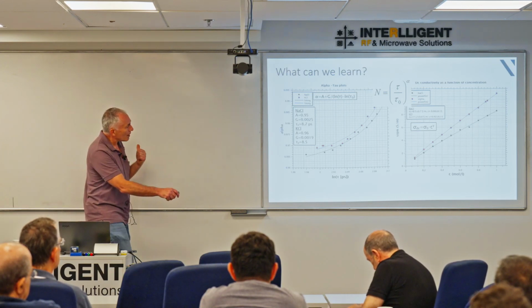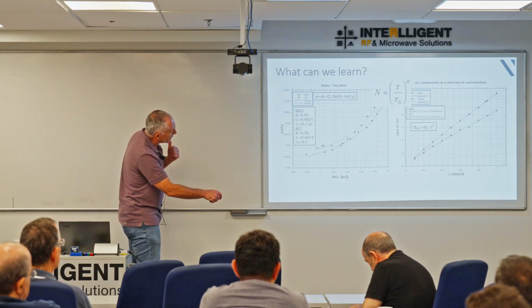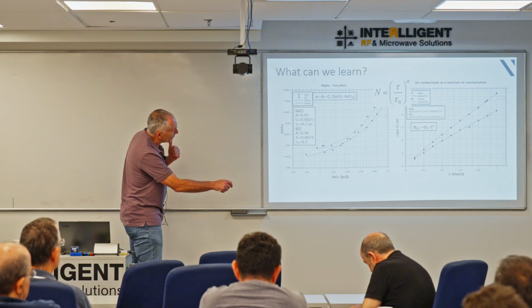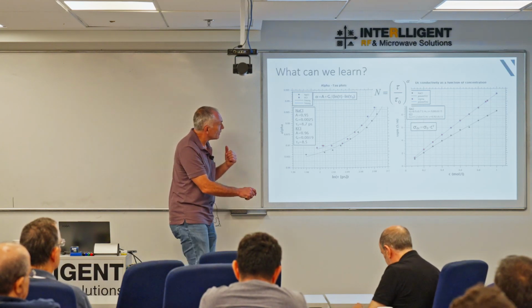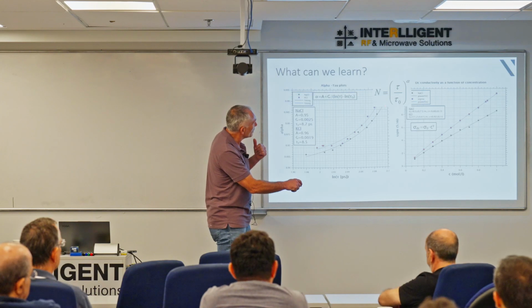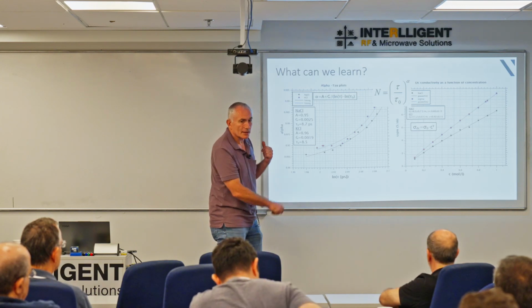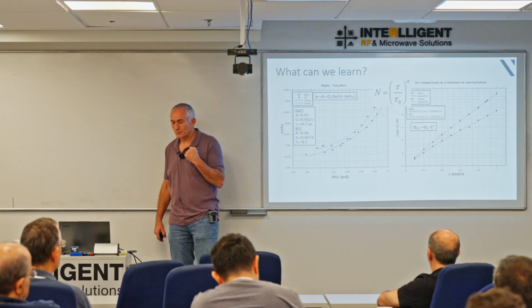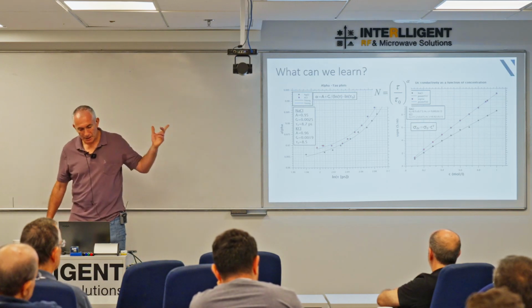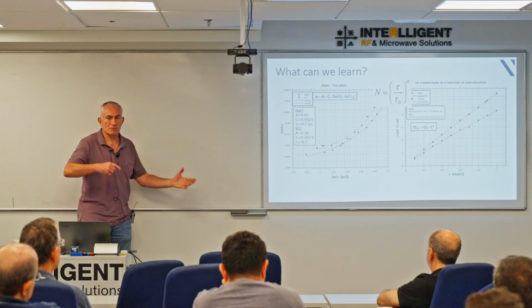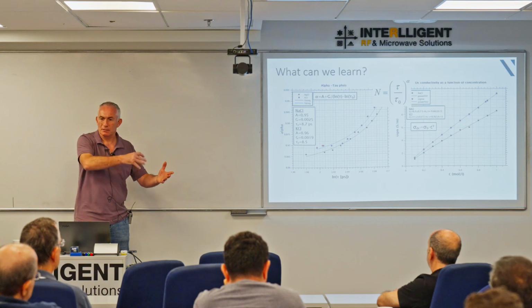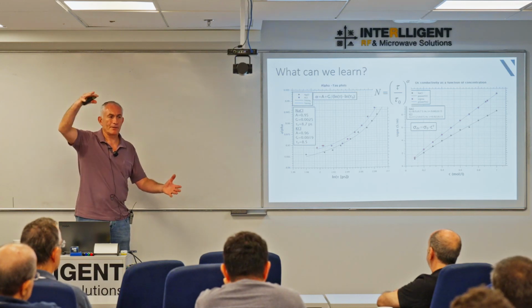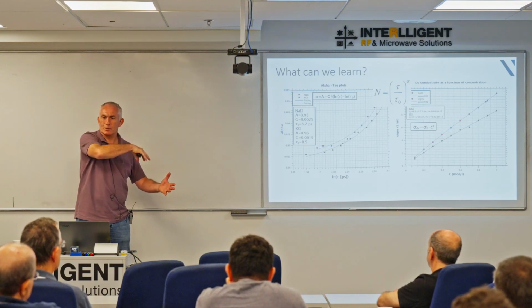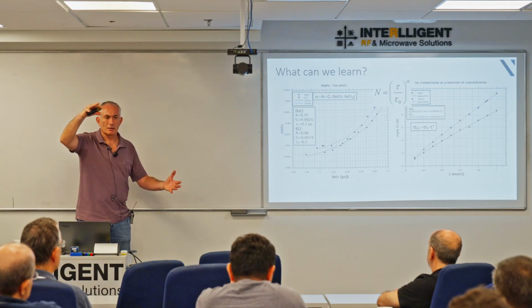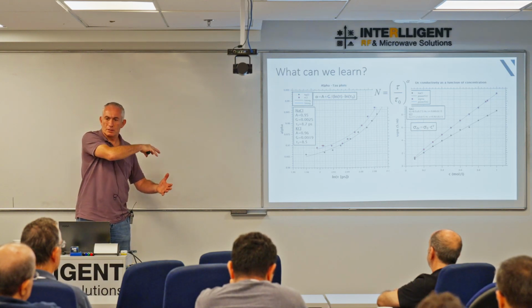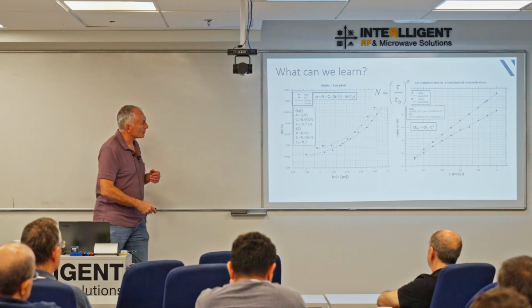And all of our relaxation times at each particular temperature that we measured up here, this is the temperature changes, yeah? All of them are faster than that cutoff time. What does it mean? Well, we have explanations what it means. It actually reflects the scaling that we have inside there. The multiple levels of different energy barriers which must be overcome between water to water when you put the salts inside.